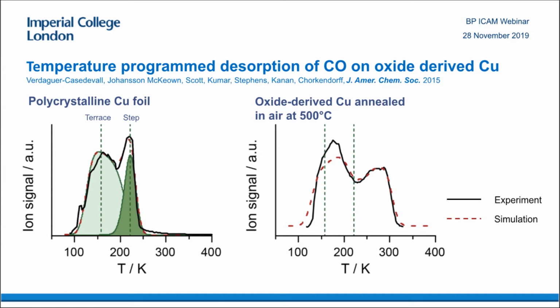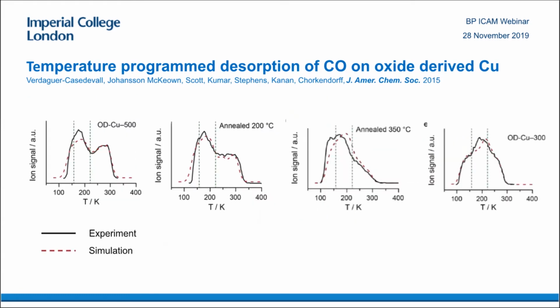Very interestingly, we saw some very strongly bound CO, corresponding to CO that desorbed at very high temperature, which we didn't observe on the polycrystalline copper. And by changing the annealing treatment, we saw more of this high temperature shoulder.